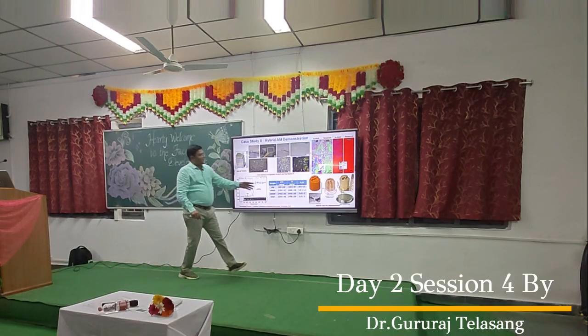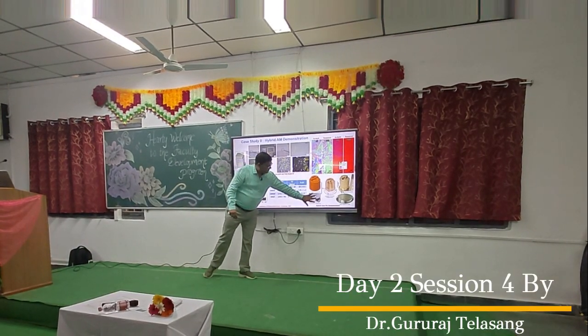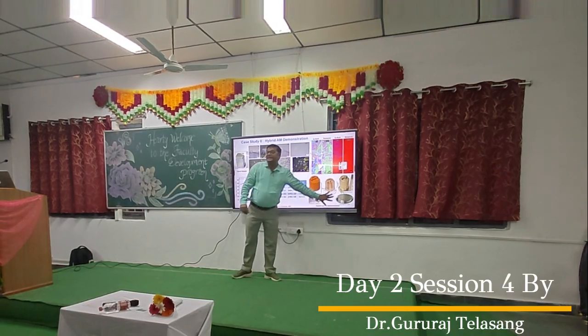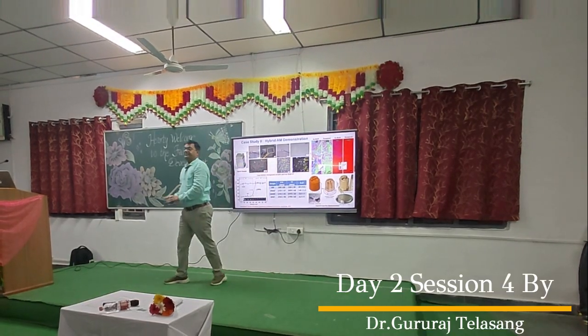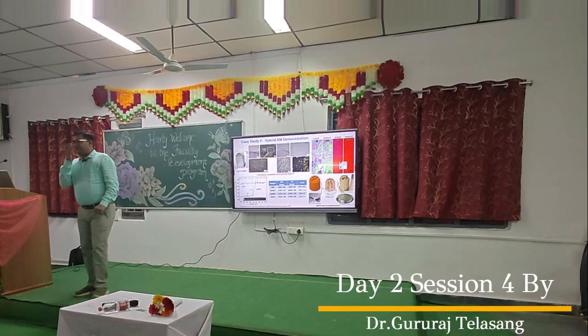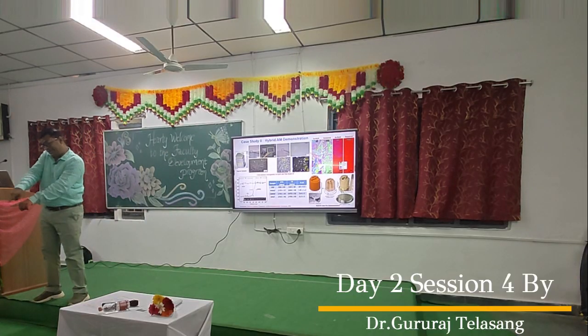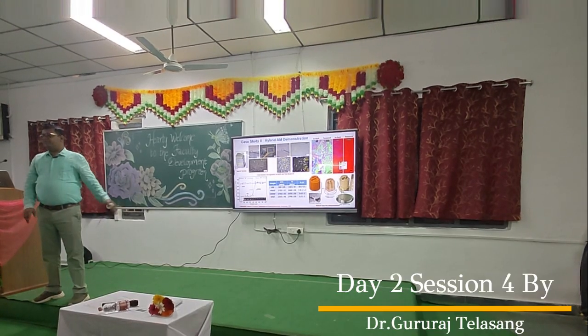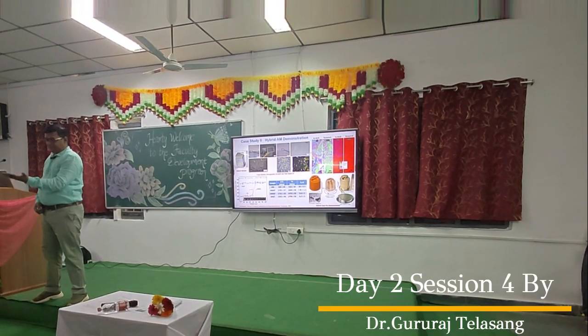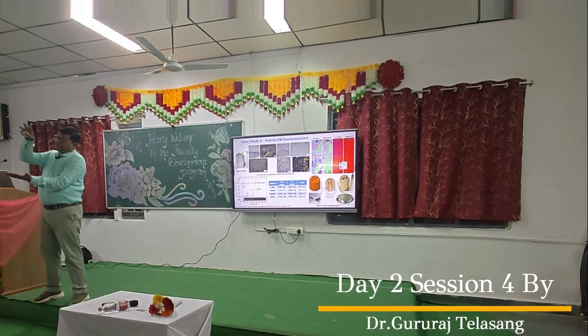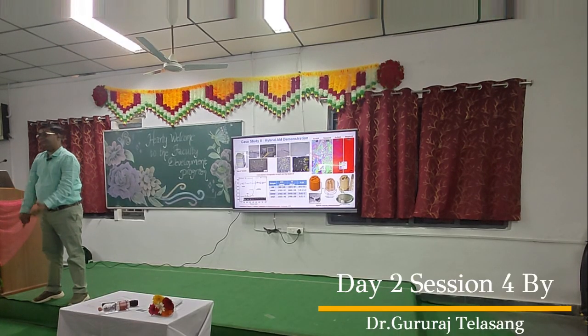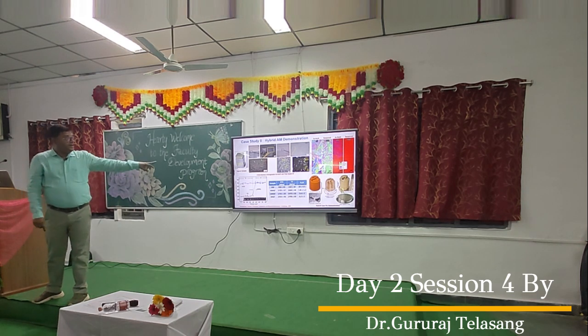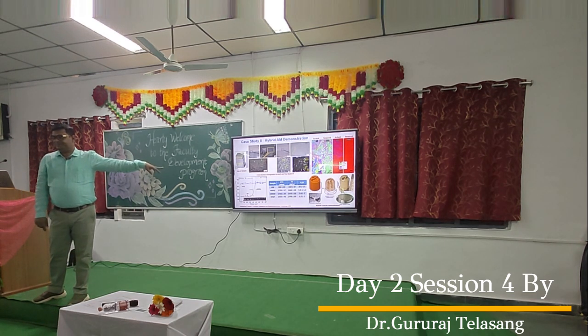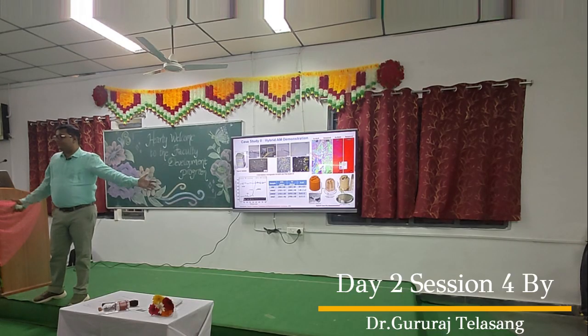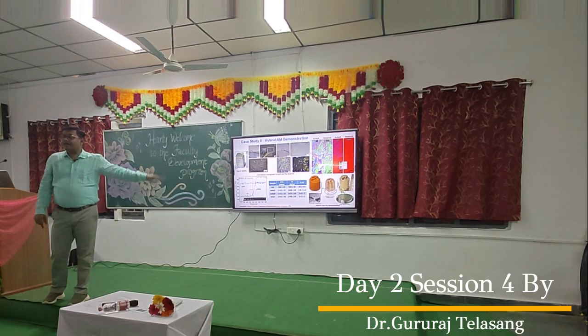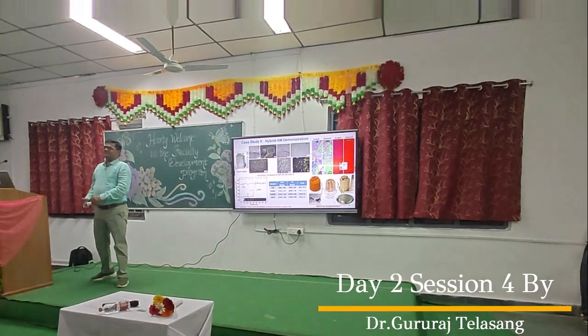So to demonstrate that, we took one conformal channel, we took a straight line, then the challenge here is you have to match them in additive manufacturing. It's not CNC or robot or something where you have 0, 0, okay, from here I will go and exactly do that. It's not happening in powder bed additive manufacturing. You have to have a 0 clamp, you have to position it. It's very challenging to exactly match that center and print on that. We tried our best with a 0 clamp. If I go to an OEM, they will charge you too much for this. So I made my own. We are in the 100 micron range. That will be covered in allowance.